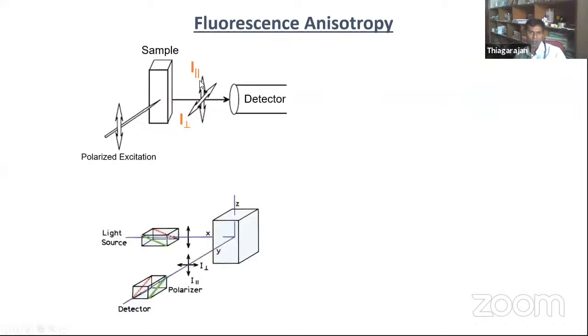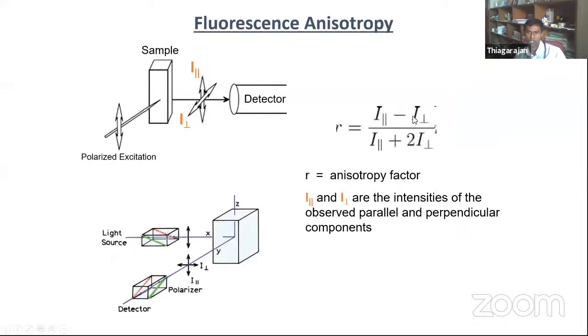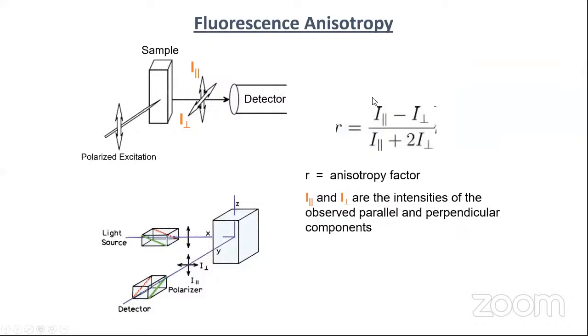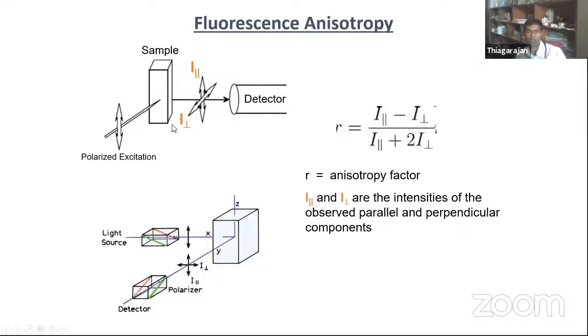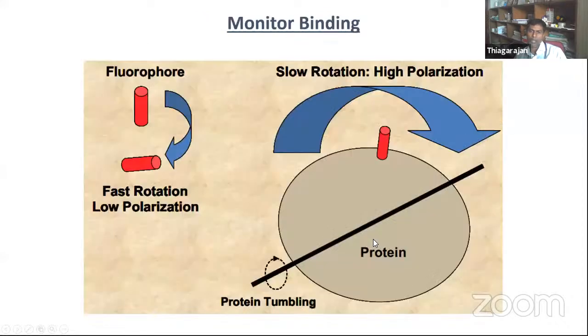In the anisotropy equation, you can see I parallel and 2 I perpendicular. Two I perpendicular because when we excite with the light, we have two perpendicular positions. The intensity dissipates into two different directions. That's the reason the total intensity is equal to I parallel plus 2 I perpendicular. Parallel is only one, but the perpendicular is two. From this, we can calculate the anisotropy and the rotational correlation time also.